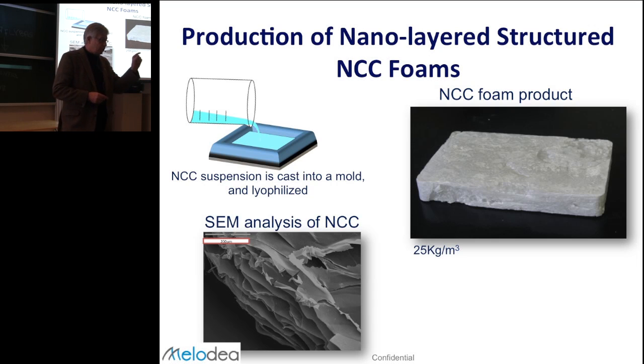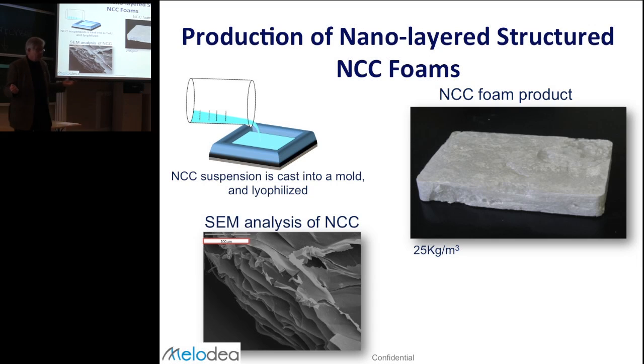And if I look upon the Young modulus, E-modul på svenska, the Young modulus of a nanocellulose fiber, it is on the same level as Kevlar, which is originally called aramid fibers, right? Which is roughly 163 GPa, and the cellulose is on that level. Right? And these nanocellulose fibers are brought together into wood. They come in different directions, and also with this amorphic region, hemicellulose in between, and it reduces the Young modulus to around 40. And 40 you have in wood, in all kinds of wood. Okay? So therefore, we developed a technique to use these nanocellulose fibers for foaming.